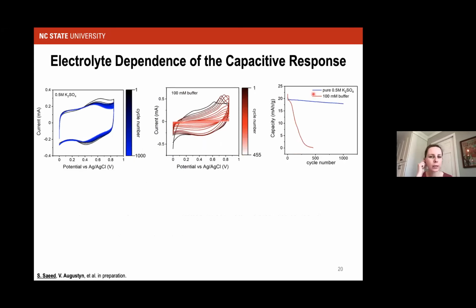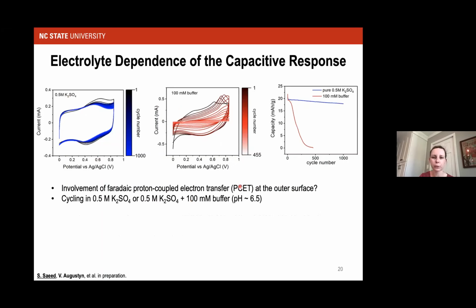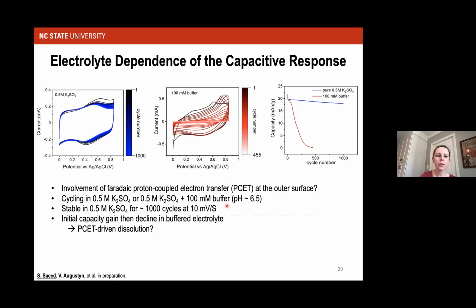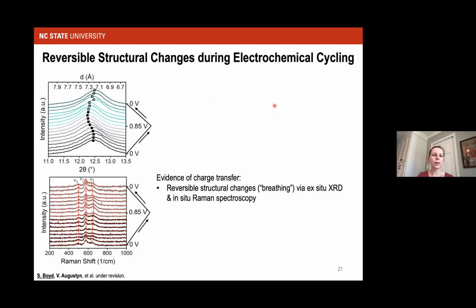So to understand whether protons are contributing some of this capacitance, we did cyclic voltammetry in both the potassium sulfate as well as potassium sulfate with a buffer, with 100 millimolar of buffer. So the pH here is maintained relatively constant or neutral. And what we see is that initially there is some capacity gain when we cycle in a buffered electrolyte, but then you see this very, very quick and sudden decrease in the capacitance. On the other hand, the potassium sulfate is very stable. Now, so we think potassium ions are what's driving the electrochemical response here.